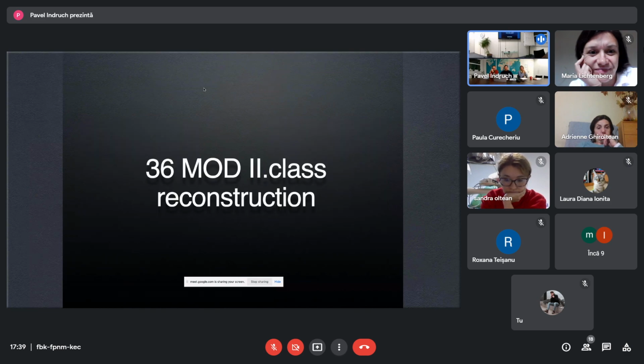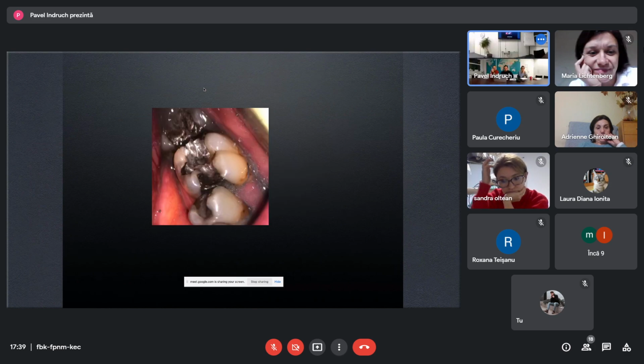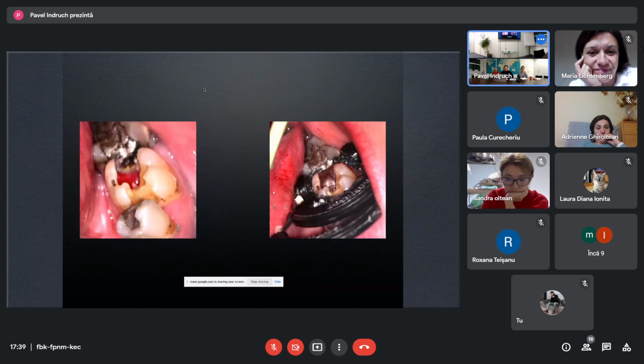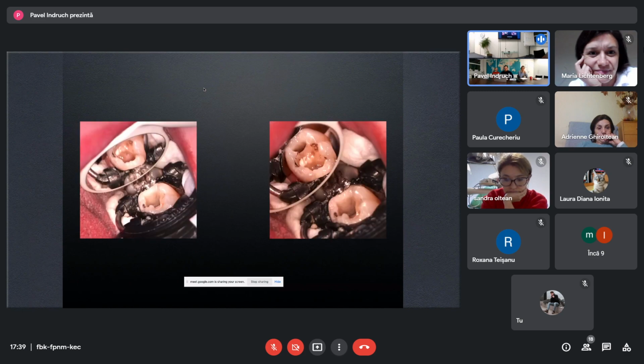This case shows 36, MOD second class reconstruction. You can see big amalgam filling. After removing, we have to evaluate if it is possible to do it only with sectional matrix or circular matrix. In this case, we used sectional matrix, 2 sectional matrix in the both proximal locations.